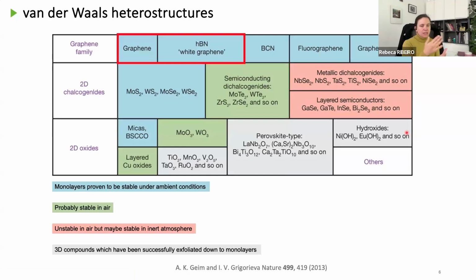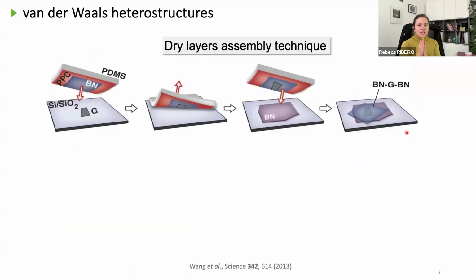So now we have all these materials, and what can we do with them? Of course we can study each one of them independently, but also, and maybe more interesting to me, we can put them together and make van der Waals heterostructures. The way van der Waals heterostructures are built in laboratories now is mostly, there are new techniques, but it's mostly through the dry layer assembly technique, which consists of taking a polymer, in this case PPC, polypropylene carbonate, and using this polymer to pick up a first layer of 2D material. In this case, it will be boron nitride, and then we're going to pick up with this one a second layer of another 2D material. In this case, it's graphene.